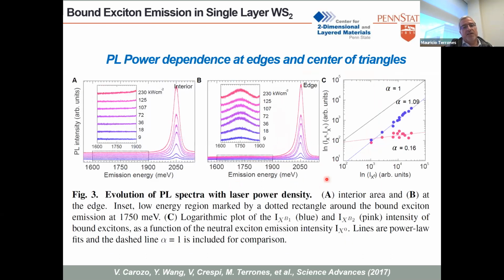One thing as well is that when you use different powers of your laser, you can pump the excitons from the regions, right? In the interior, as you don't have many vacancies, as you increase the power, you don't pump any excitons. But at the edge, when you start increasing the power, you start to pump excitons, and you can see this bound exciton intensity increases. We can correlate this to this system. This is the bound exciton, and this is the neutral exciton, right? So we can see the two excitons and the linear behavior.